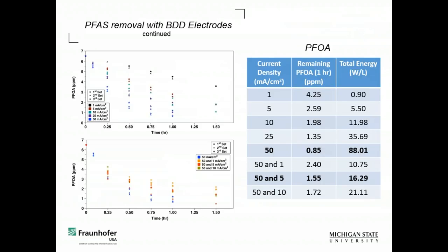But here's some of our data. So I have PFOA on this slide, PFOS on the next slide. So like I said, before I get into this, we are after two applications. We are not treating groundwater plumes, we're not treating drinking water, and we're not an end of pipe treatment method at a wastewater treatment plant. If you look at this graph, here's 50 milliamps per centimeter squared. In an hour, we've taken it from 6 ppm down below 1 ppm. So if we run these tests for just about another half hour, 45 minutes, we can effectively get all of this out.